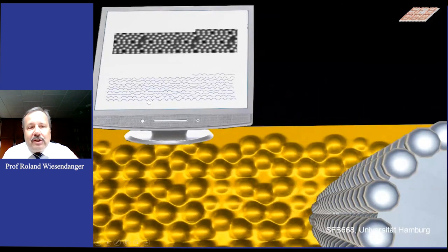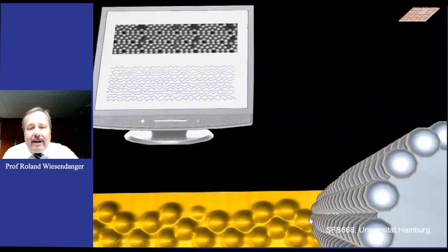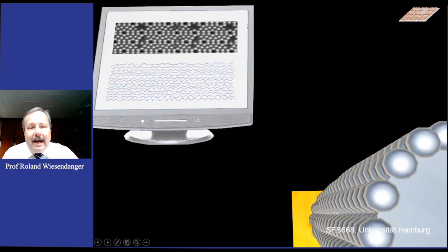The magnification comes along because the very tiny distances you scan with your tip are magnified to the macroscopic screen of your computer. And then you can also translate the height information of these line traces to a grayscale image. Then you see much better very nice atomic scale structures, usually some periodic patterns, of course also with some atomic scale defects, which you can recognize here. So you get a very nice impression of the atomic scale structure, in this case of a silicon surface.